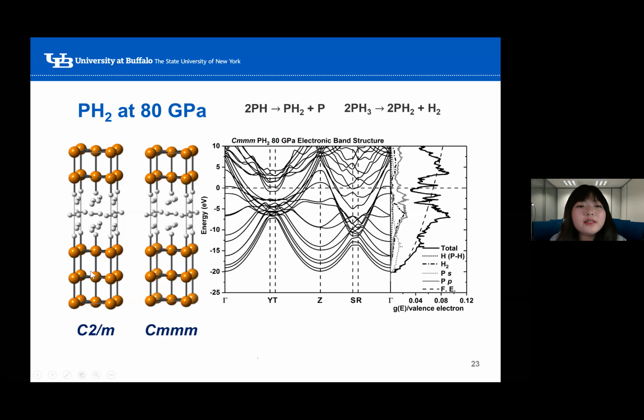So these two phases are structurally related again. The major difference is the orientation of the molecular hydrogens. And also, in the C2/m phase, the PH bond is slightly tilted, resulting in, again, more efficient packing and a smaller PV contribution to the enthalpy. However, because the electronic contribution favors the Cmmm structure, these two structures are almost isoenthalpic. At 80 GPa, both of the structures are metallic and almost free-electron-like.